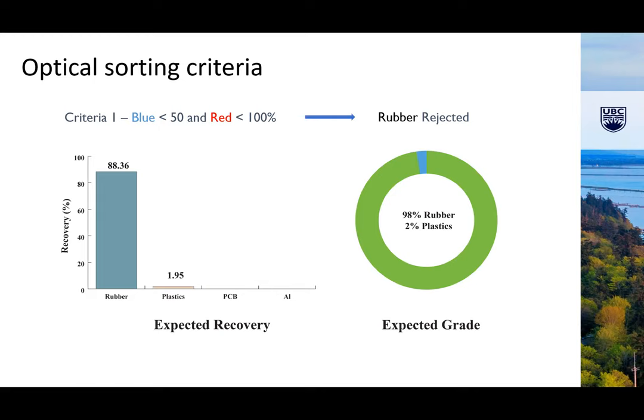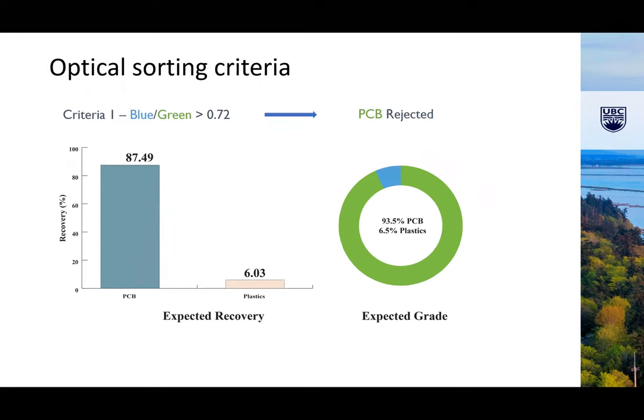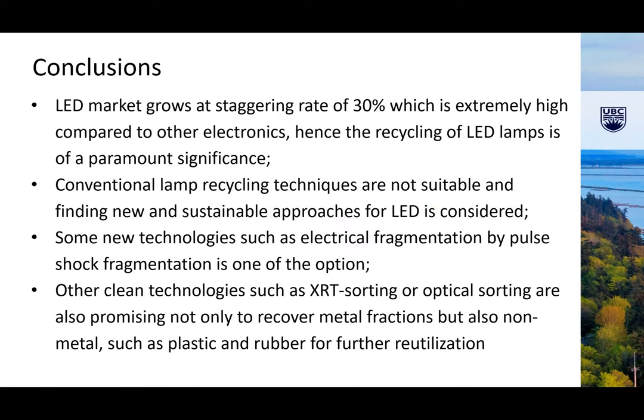98% with 89% recovery. It means from the mass coming in, almost 90% was sorted out. So this is pretty good. So we were able to reject rubber, and the product that we ended up with was 98% rubber and 2% plastic. Another criteria set up according to the graphs that we generated from the RGB data, we could actually reject the PCBs with 93.5% content with almost 88% recovery. So this is pretty impressive.